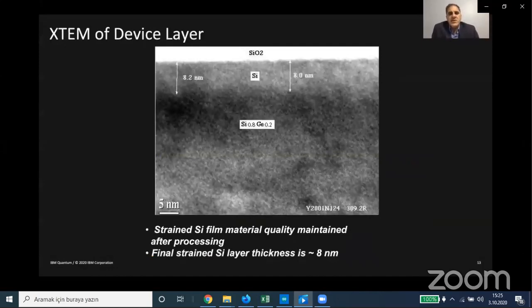Shown here is that the silicon layer on top is preserved. Also, in addition to these low temperature steps, good care had to be taken to preserve the integrity of the silicon surface on top so that a high quality interface between the silicon and silicon dioxide was formed, and hence a working gate for the MOSFET.